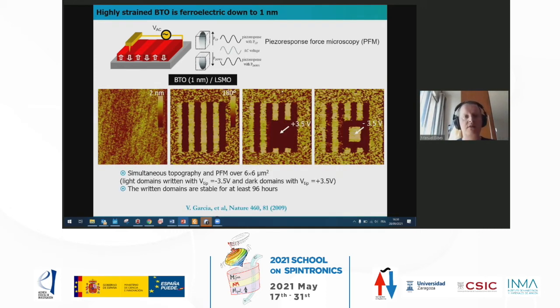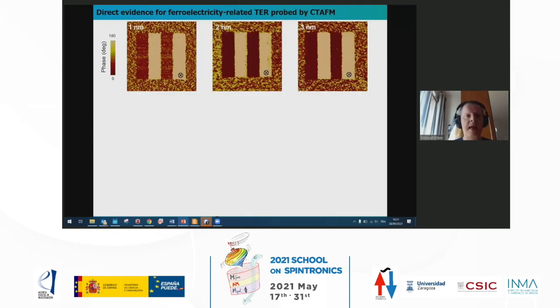So we did that on different samples, and this is an example for a 1 nanometer barium titanate sample. And you can see here PFM images of domains that we wrote with the tip. And we can switch them back and forth. Everything looks nice and okay. And they are stable over time, which was not a given because this barium titanate was very, very thin, just 1 nanometer. So we did that for 1, 2, and 3 nanometer samples.